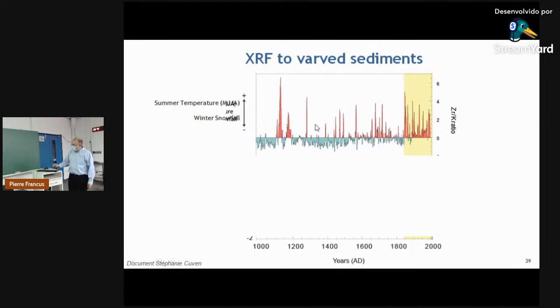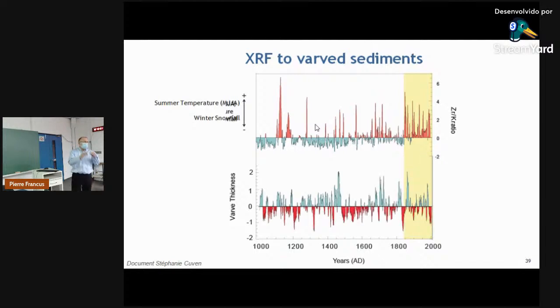Now, what is very interesting is when you compare the Varves thickness record taken from the same core, and you see this is normalized Varves thickness, and you see that we have a story that is completely different. And why this is the story that is completely different is because we have rain events, and the rain events are adding some sediment thickness to the Varves thickness. So basically, it is by combining different kinds of proxy on the Varves that you can have a better and more complete idea of the climate.